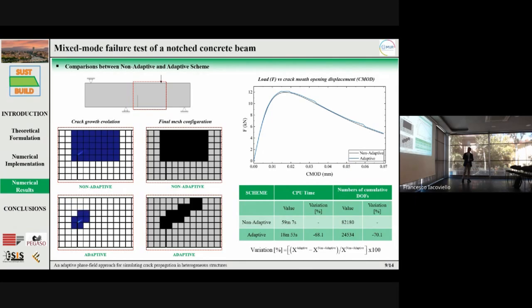In addition, the adaptive approach provides a more efficient simulation, because it significantly reduces the computational time, with a reduction of about 68%, and the number of cumulative degrees of freedom, with a reduction of 70%. This occurs because, as we can see from the crack growth evolution and the final mesh configuration, the adaptive scheme dynamically refines the mesh only in the region where crack propagation takes place.